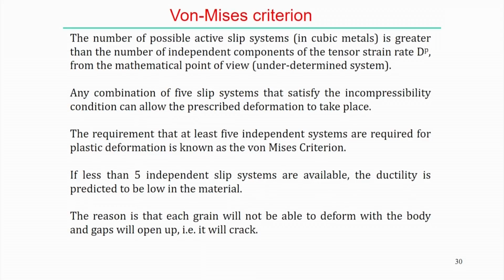The number of possible active slip systems in cubic metals is greater than the number of independent components of the strain rate tensor, that is represented by dP, from the mathematical point of view. Any combination of the 5 slip systems that satisfy the incompressibility condition can allow the prescribed deformation to take place. So we have discussed the requirement that at least 5 slip systems are active at a time, so that it can maintain the incompressibility condition.